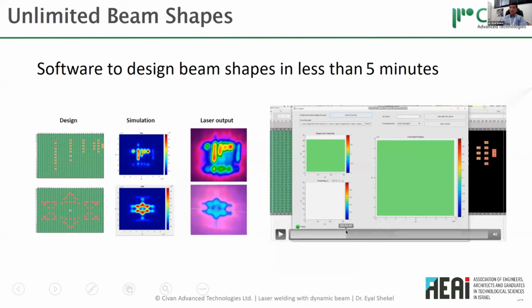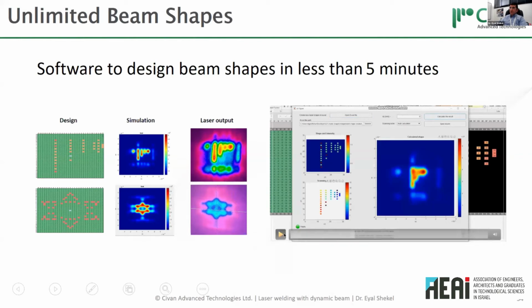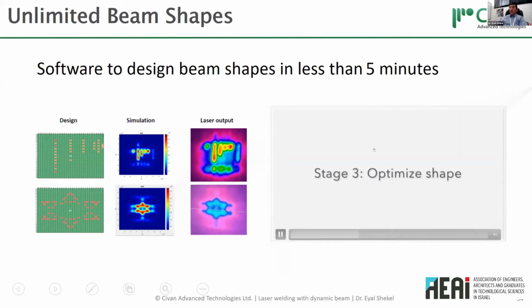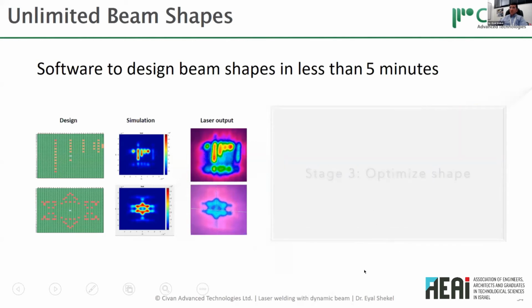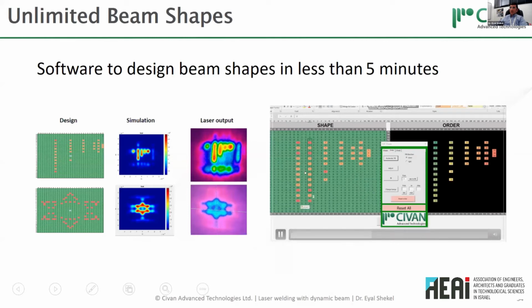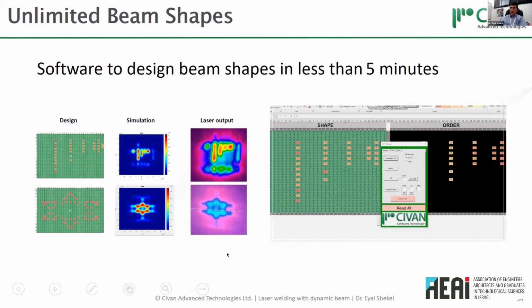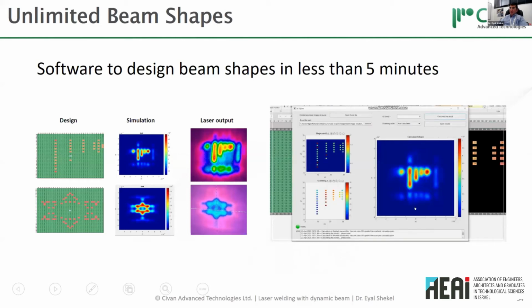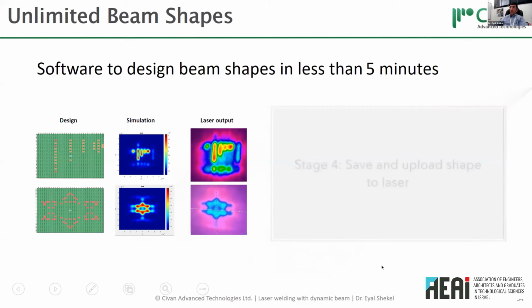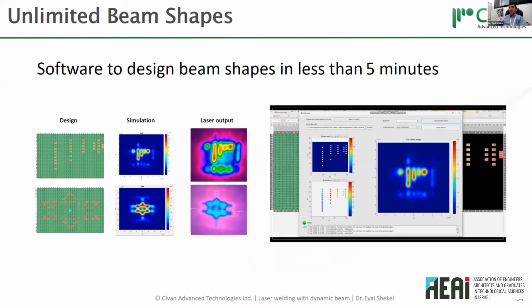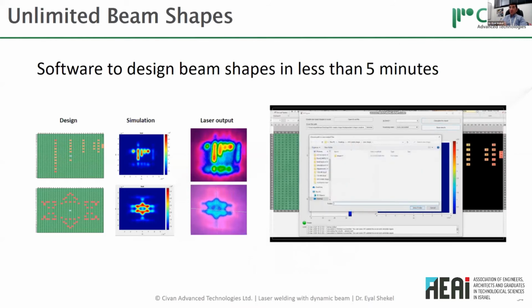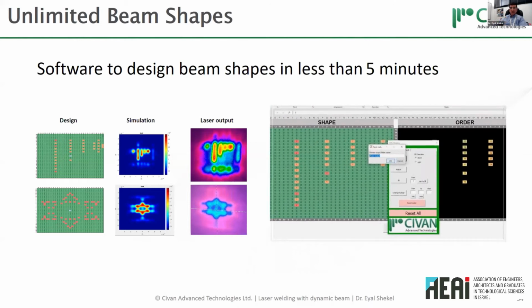So you can see here that the shape was not perfect. Okay, in the simulation, you get a shape that is not exactly what we wanted. So we can go back and do a little bit of optimization to the beam shape, move things around a little bit, change the intensity in every area, and get a simulation of what the beam is really going to look like. And then all you have to do is upload this file into the laser, and then you can just pull it from the laser anytime and you get this beam shape.